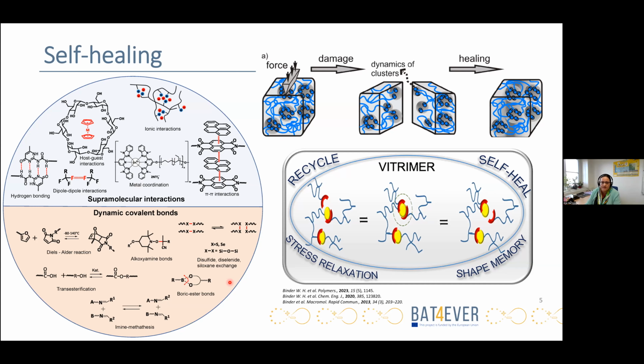via dynamic covalent bonds. Supramolecular chemistry is based on reversible non-covalent bonds, which primarily break upon mechanical damage or stressing, leaving behind a kind of sticky functionalities which are preserved on the freshly formed interface after the cutting. That means these sticky parts are actually multiple unbonded supramolecular bonds, which then can rearrange, recombine, and restructure in order to heal the material.